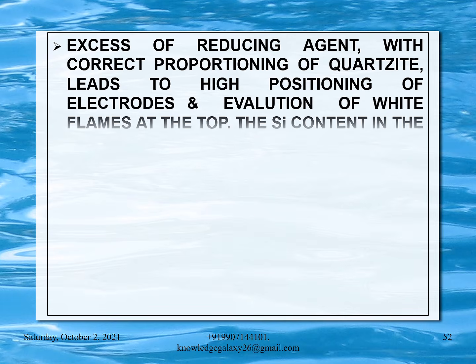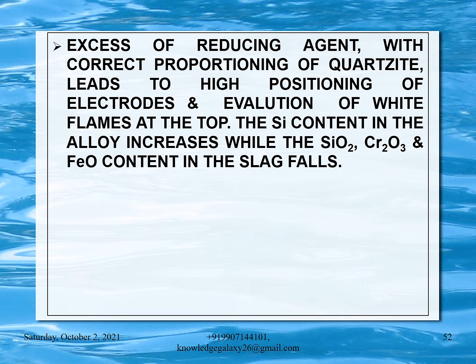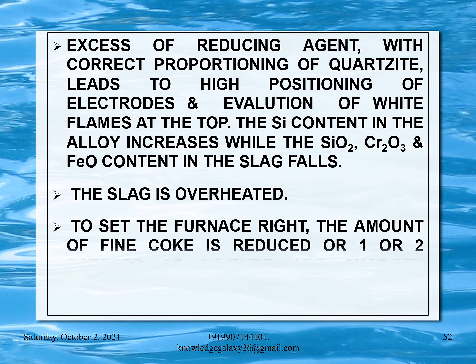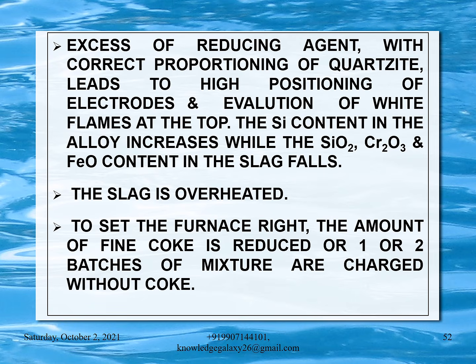Excess of reducing agent with correct proportioning of quartzite leads to high positioning of electrodes and evolution of white flames at the top. The silicon content in the alloy increases while the SiO2, Cr2O3 and FeO content in the slag falls. The slag is overheated. To set the furnace right, the amount of fine coke is reduced or one or two batches of mixture are charged without coke.